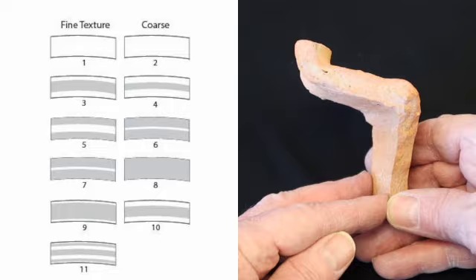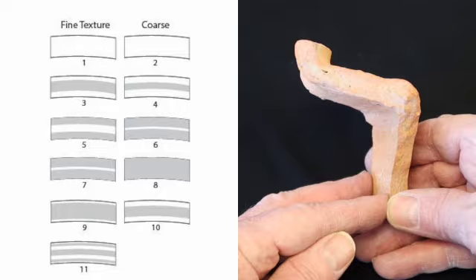This sherd is evenly fired all the way through, showing that it was fired in the kiln with an oxidizing atmosphere, while this one shows much the opposite, being oxidized on the outside, but very reduced on the interior,